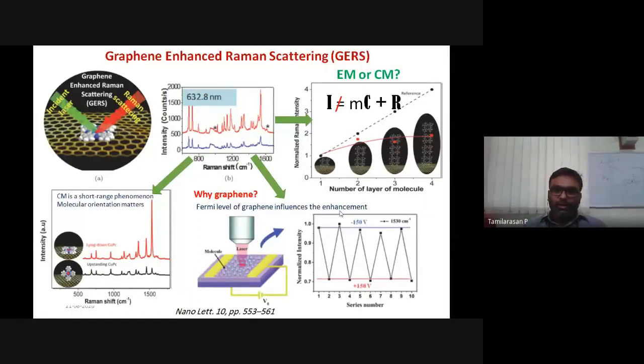You might have seen the parabola of the transfer curve of graphene transistors. So they took two different potentials on the two sides of the Dirac point. They found that when you change the Fermi level of graphene by applying potential, you are actually changing the intensity of the Raman signal from a molecule. So if the Fermi level is changed, obviously you are changing the charge transfer kinetics. If the Fermi level matches very well with your molecular energy levels, then you will get a better signal. This is how they tuned it, and they proved through all these three mechanisms that graphene is assisting in the enhancement of the Raman signal through chemical enhancement.